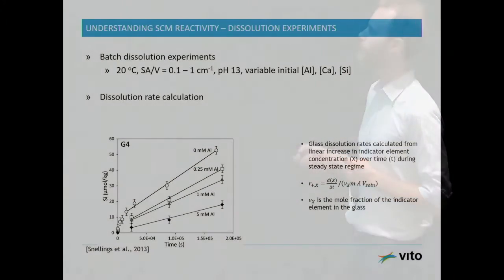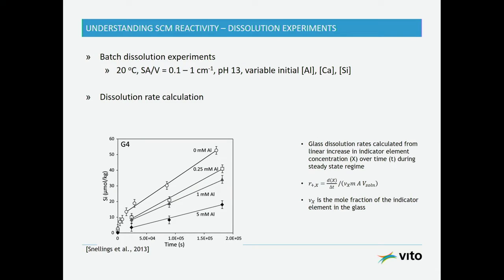So how does it work? Well, we did some batch dissolution experiments. So we added the glasses into a large volume of water. We fixed the pH to 13, and then we added, for instance, aluminum, calcium, silicon, to see what the impact of these ions in solution would be on the dissolution rate.